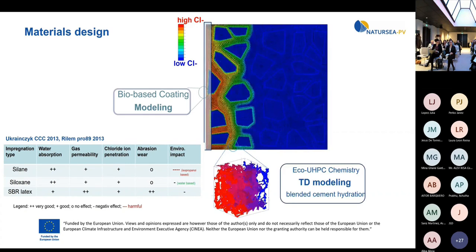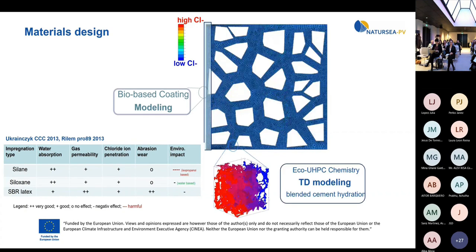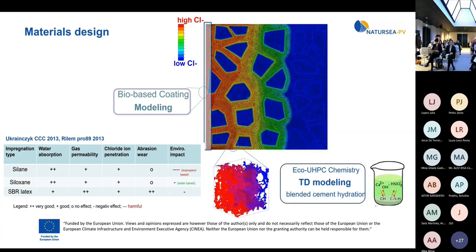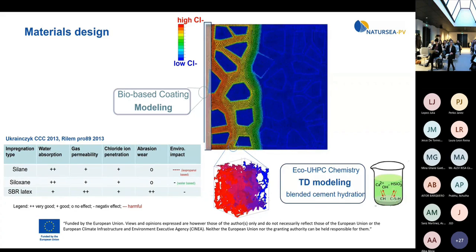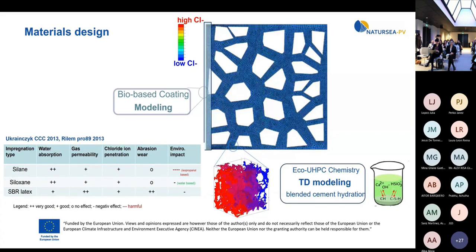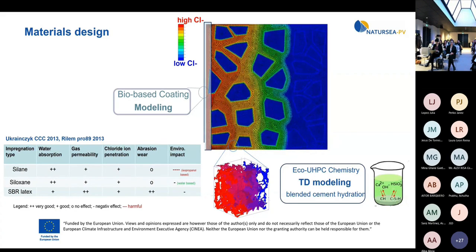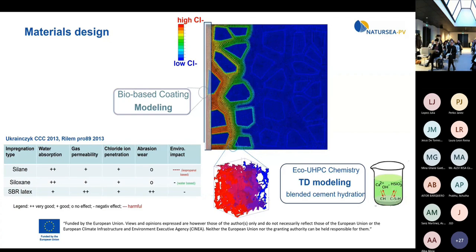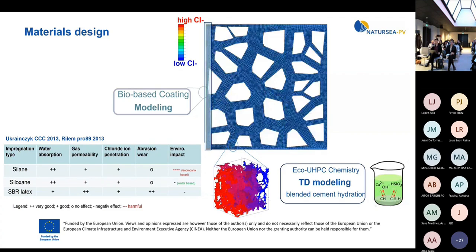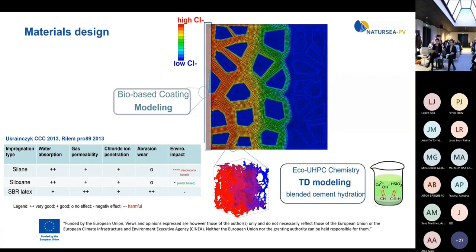Yeah, and now the paste, here we have the thermodynamic modeling, so that we can predict how the supplementary cementitious materials, how the eco-cements, what is the best eco-cement solution, because we need a microstructure to replace the cement. We can use this very powerfully with the thermodynamic modeling, because then we can predict the phase assemblage, we know the porosity, we know which kind of phases are forming.